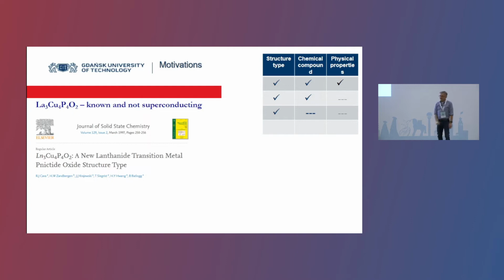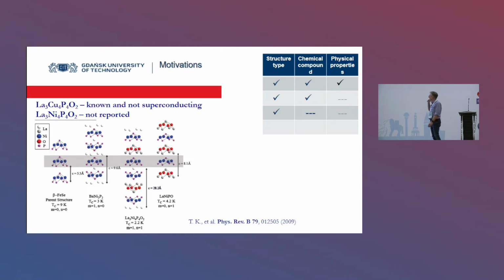The strategy number 3: the structure type is known. So we know the structure type, and we replace 1 or 2 atoms, or 3 atoms. This is a paper from 1997 from Bell Lab. Bob Cava published a paper about lanthanum 3 copper 4 phosphorus 4 O2. And a few years later, when all these iron arsenides were published or studied, I went back to this paper and I found that possibly copper can be replaced by nickel. And we made lanthanum 3 nickel 4 P4O2 with Tc 2.2 Kelvin. Okay, Tc is still low, but anyway, that's another example, another material in this big family of the iron oxyarsenides or iron arsenides, nickel arsenides, and so on and so on.